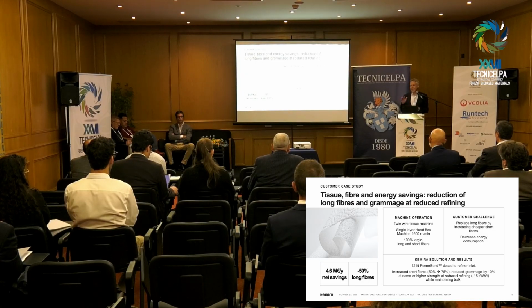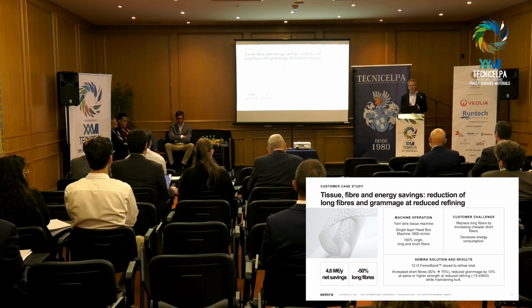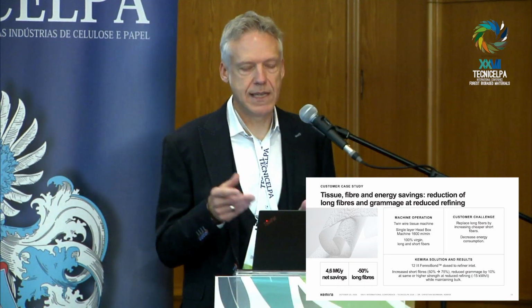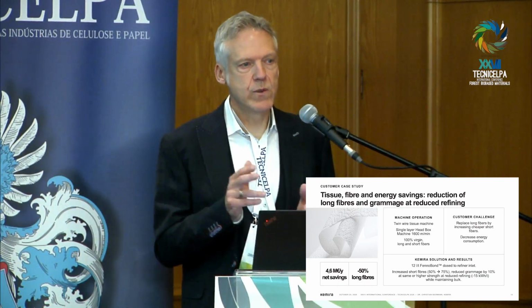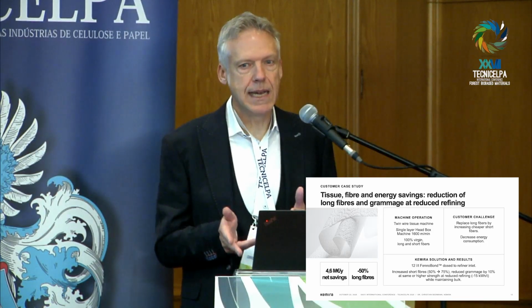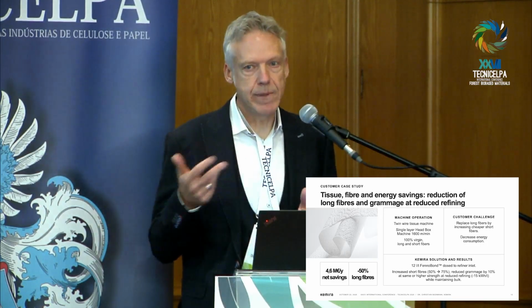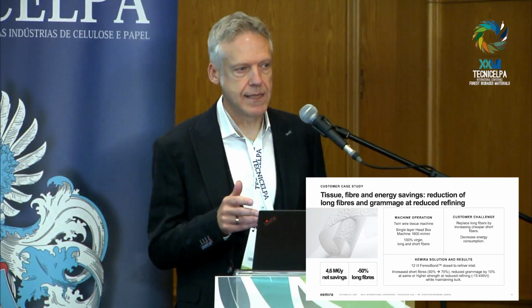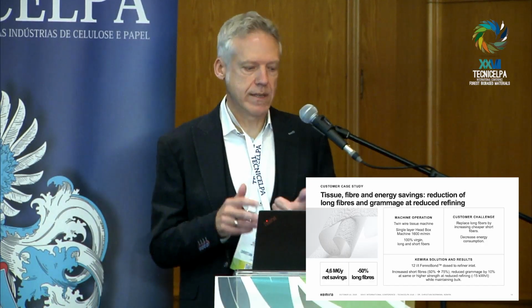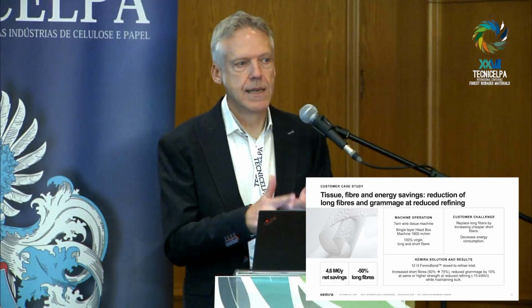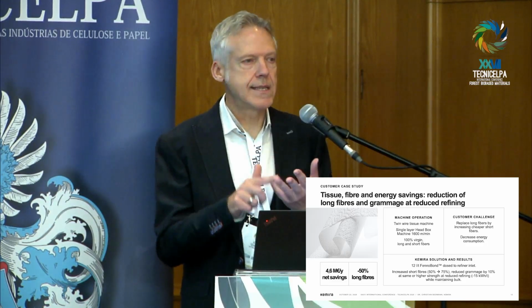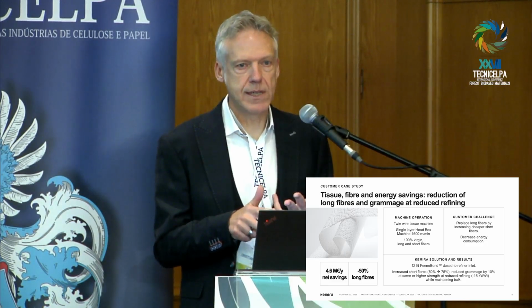Daniel said that it's sometimes 4 or 5% of long fibers in the tissue production here, so very different maybe. But what was nice, they could decrease the refining of the long fibers as well. That of course generates a little bit of energy savings, but that's not a lot of money. But due to the reduced refining, they gained bulk at the same strength, and that enabled them to reduce the grammage by 10%. And so they got less refining, less long fibers, more bulk, and with this the ability to reduce the grammage by 10%.